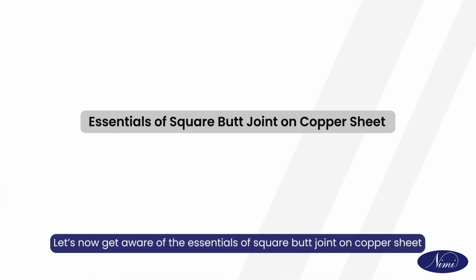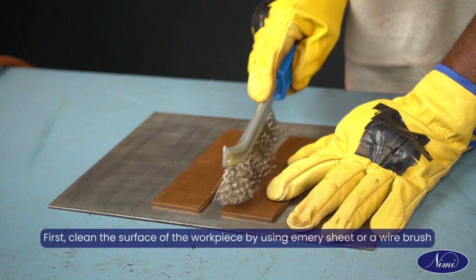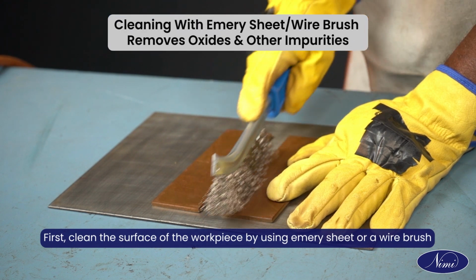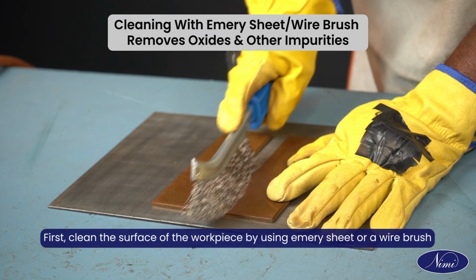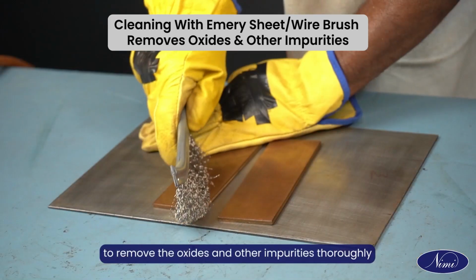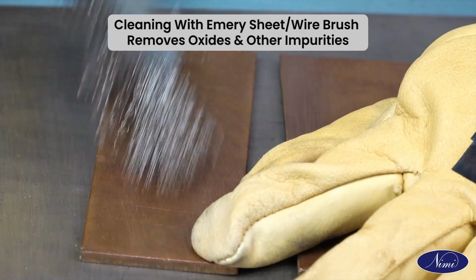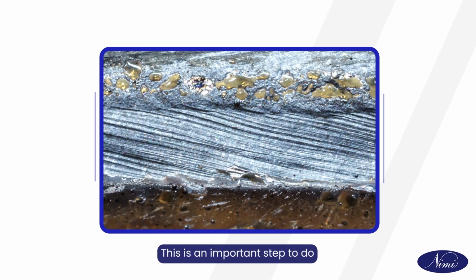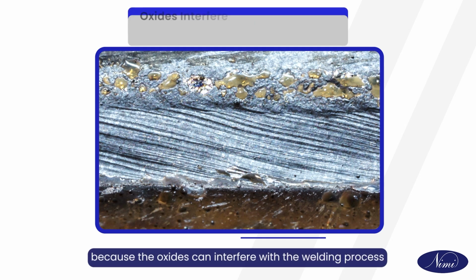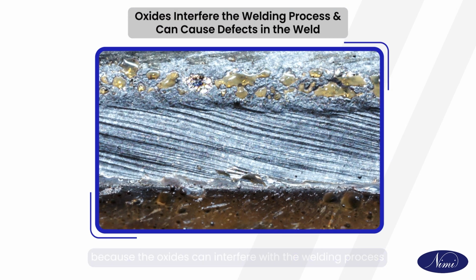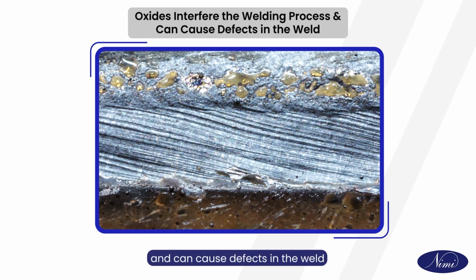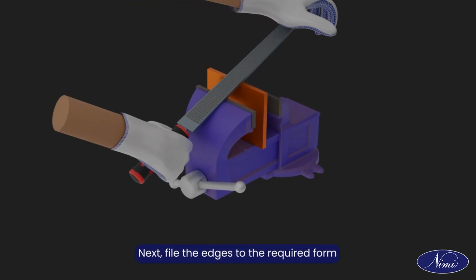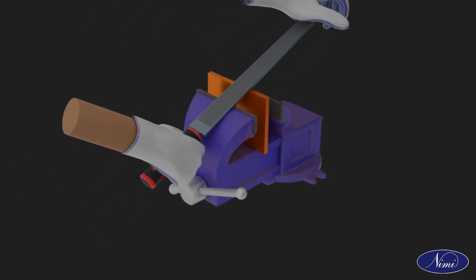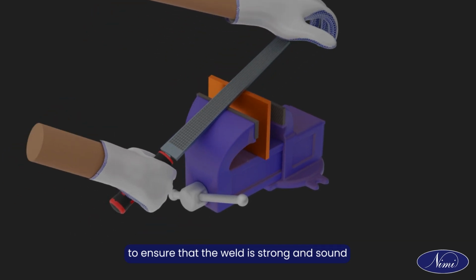Let's now get aware of the essentials of square butt joint on copper sheet. First, clean the surface of the workpiece by using emery sheet or a wire brush to remove the oxides and other impurities thoroughly. This is an important step because the oxides can interfere with the welding process and can cause defects in the weld. Next, file the edges to the required form to ensure that the weld is strong and sound.